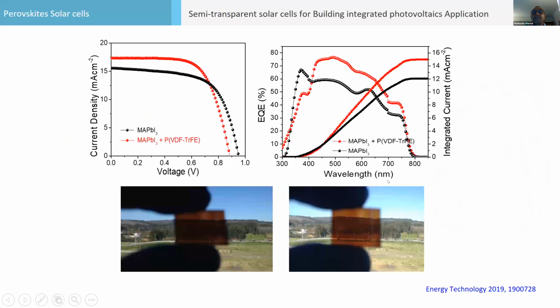This is the last slide. Let me show you the use of a polymer, PVDF, because polymers can also increase stability. Here, on purpose, we chose a very thin perovskite thickness of 150 nanometers for other applications like BIPV, and we deposit a polymer on top of it to encapsulate the devices and increase the stability. PVDF is a dielectric polymer, which we observed increases the efficiency, and the device performance was very much increased there.